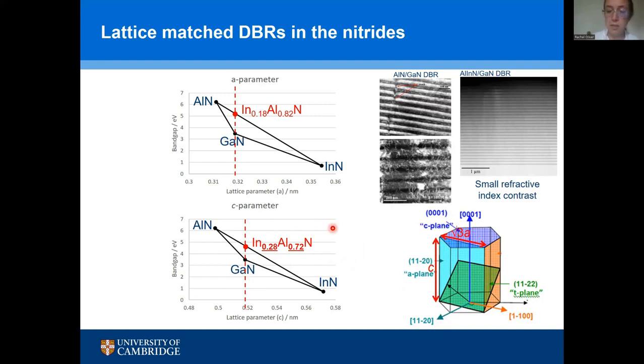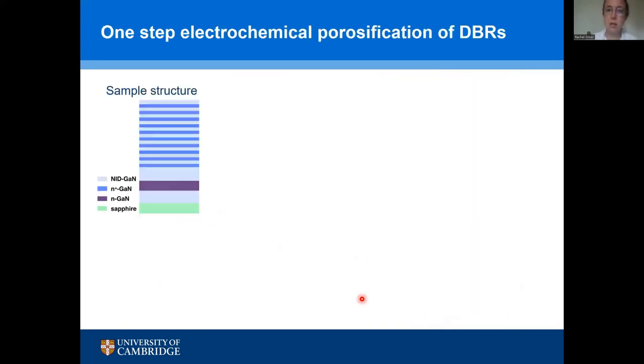So there are ways we might want to grow our crystals in gallium nitride where there is simply no option for a lattice matched material because of the special symmetry, or in fact lack of symmetry, of the gallium nitride crystal. So that's where we started thinking, right, okay, we need an alternative approach. We have these A-plane materials where we can't use any kind of lattice match pair. So instead, we're going to make porous gallium nitride.